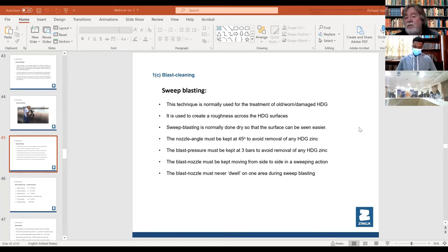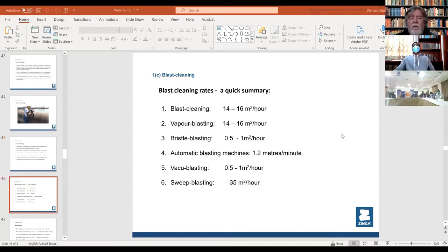So you sweep blast and it's fast. It's 35 square meters an hour, which is double the normal blasting speed. Because you're sweeping so quick, it knocks everything off and then straight on with the Zinga, straight on. And that's it. It's there for the next 30, 40 years again. So you can re-galvanize things at a very high speed. So these are your cleaning rates. This is a summary. So the first two are the normal ones. And then, as I said, bristle blasting is very, very slow. Vacuum blasting, very, very slow. And your sweep blasting is very fast.